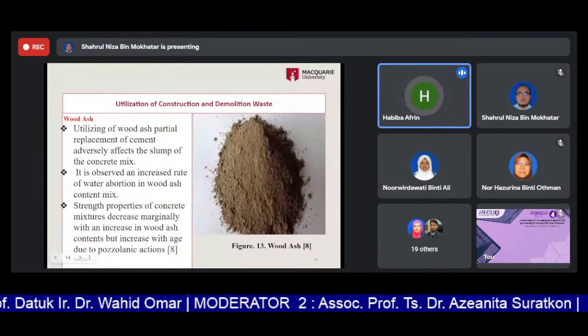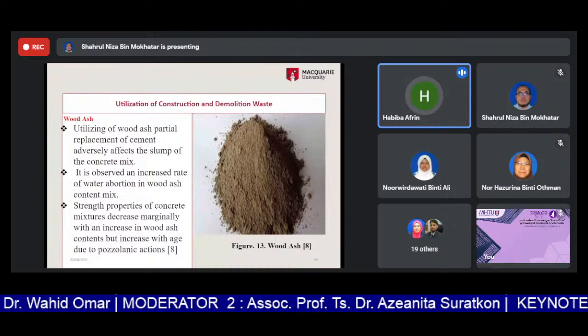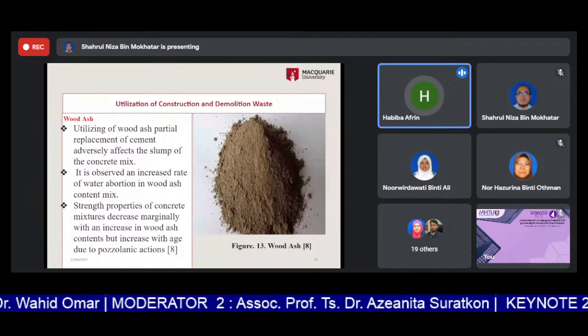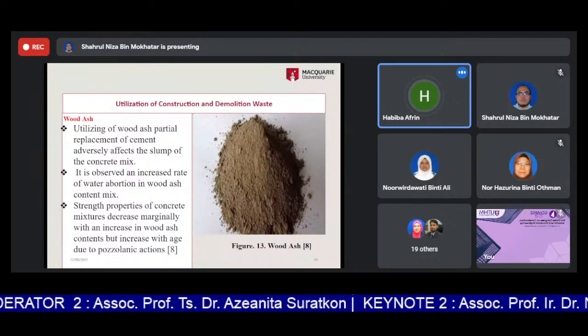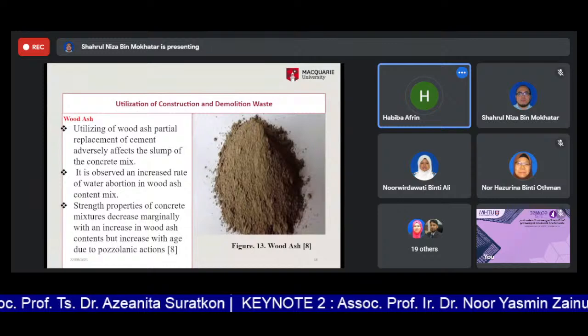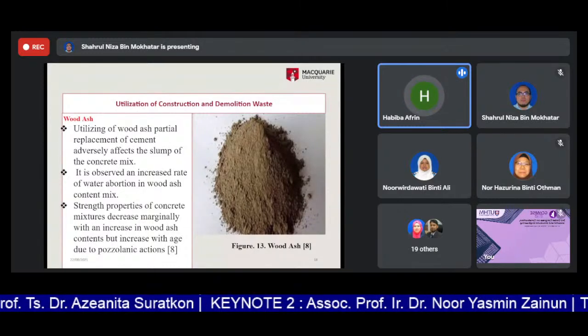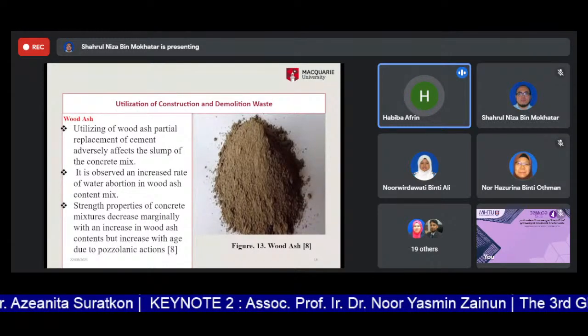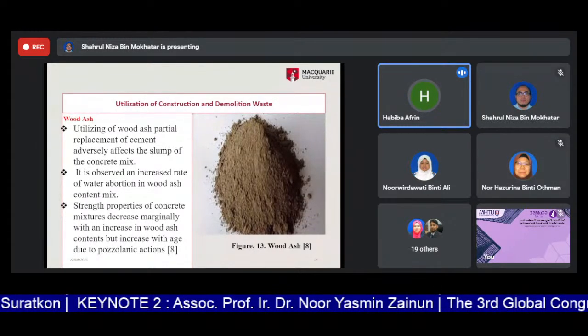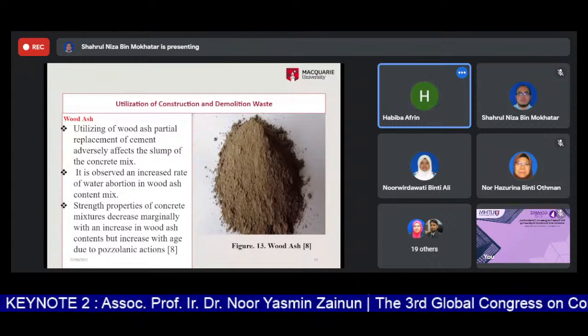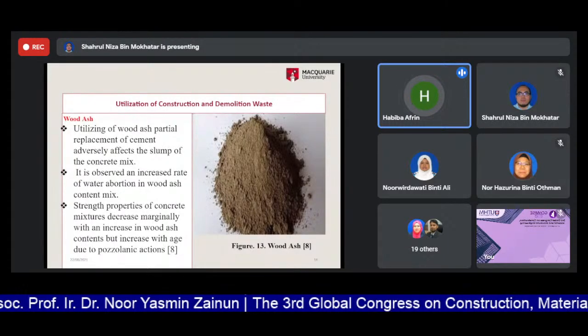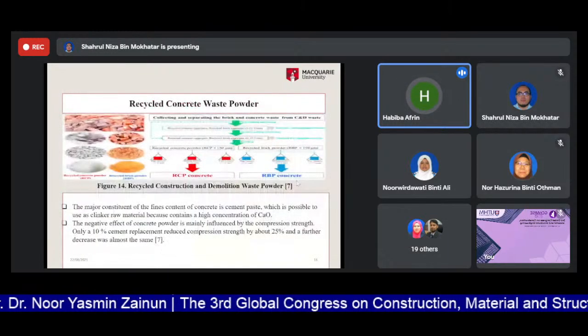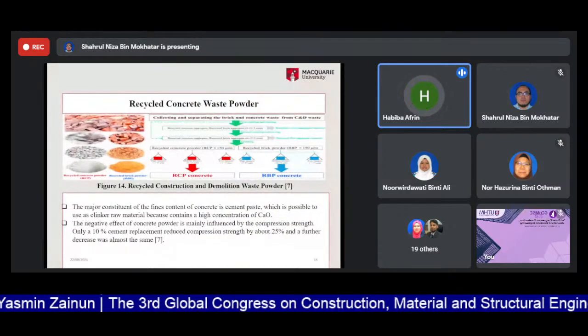Another construction and demolition waste is wood ash. When utilizing wood ash as a partial replacement of cement, an increased rate of water absorption in wood ash concrete mix is adversely observed. Strength properties of the concrete mixture decrease marginally with an increase in wood ash content, but increase with age due to the pozzolanic actions. We have another recycled material, which is concrete.